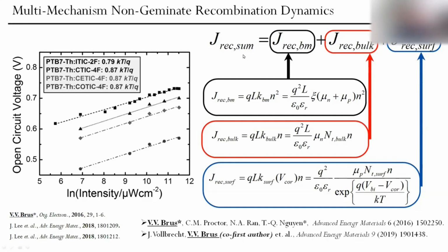It's like the total recombination loss in an organic solar cell, which includes all mechanisms of non-geminate recombination. So this is after the step of geminate recombination. By the way, it is worth mentioning that geminate and non-geminate recombination differ not only in mechanism, but also in time scales. Recombination of charge carriers originating from the same exciton at the interface of donor and acceptor happens very quickly, within up to 1 nanosecond.